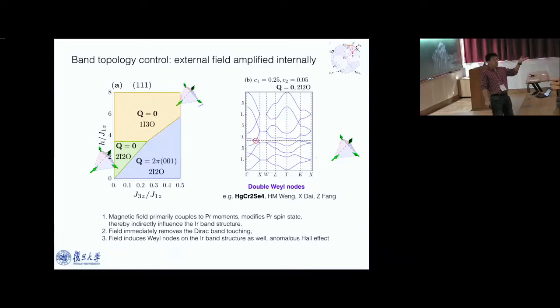Now we talk about the magnetic control of the topological band structure. Imagine you apply a field to the system. For a system with local moments and conducting electrons, the conducting electrons form a Fermi surface. The local moments are localized, and if I apply a field, the predominant effect is the Zeeman coupling to the local moments, not the coupling to the conducting electrons. The reason is there are many more local moments than electrons on the Fermi surface. So the dominant effect is the coupling to the local moments.